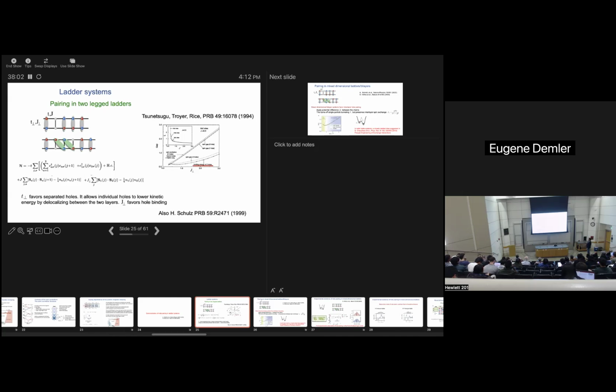Well, it looks like a reasonable argument, except that it's actually somewhat suspicious, because it's true that we can save on the exchange energy between the chains. However, the penalty that we pay is that now these holes cannot move independently from each other. So we gain on the superexchange energy, but we lose on the energy of tunneling. And actually J we introduced as a higher order correction, like in perturbation theory in tunneling. So it's not obvious that the gain in exchange should overcome the increase in energy in t perp.